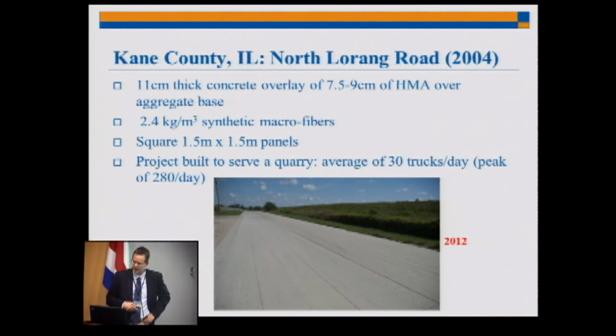This is a project right outside the city of Chicago near an aggregate quarry. Again, 1.5 meter panels here, 2.4 kilograms of fibers. And this project, after 8 years when we saw it, really no cracking, looks really good.